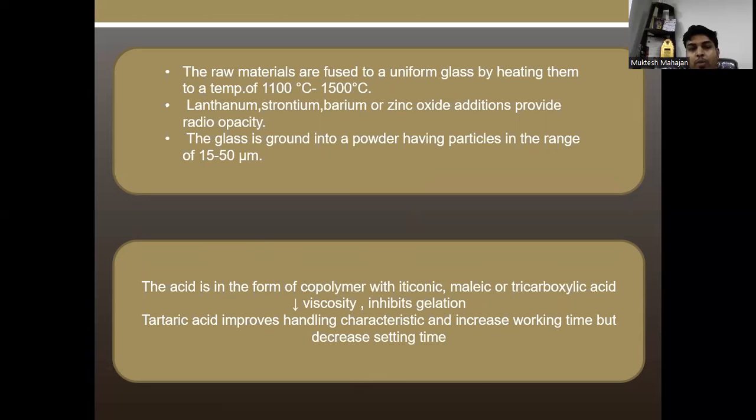The acid is in the form of a copolymer with itaconic acid, maleic acid, and tricarboxylic acid. This causes a decrease in the viscosity and inhibits gelation. Tartaric acid improves the handling characteristics and increases the working time, but decreases the setting time.